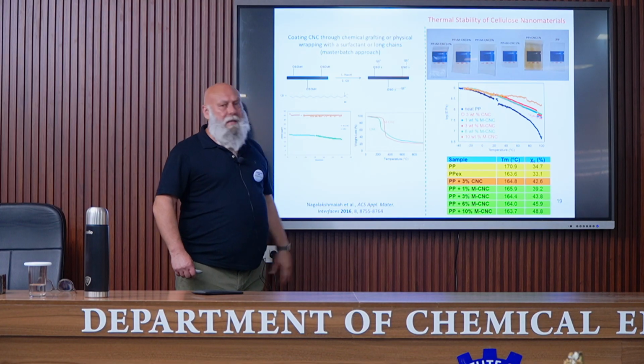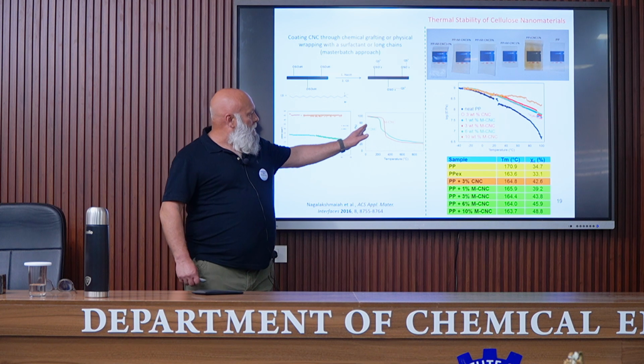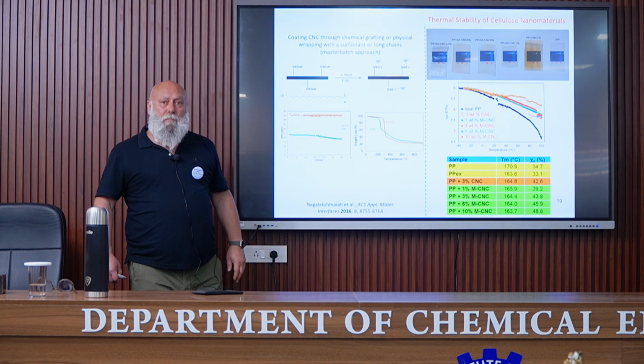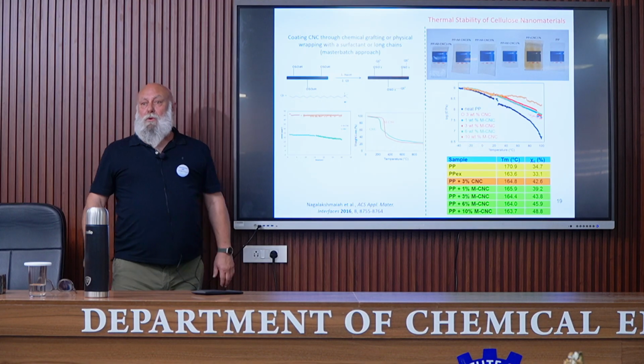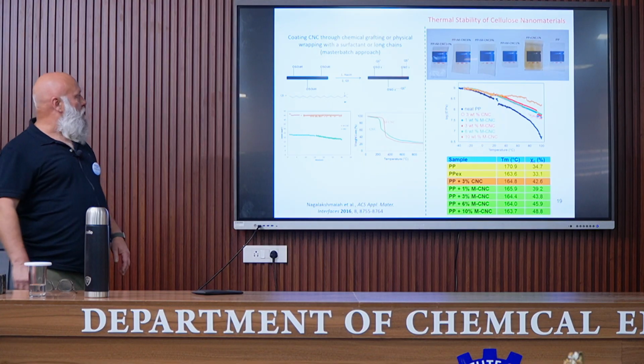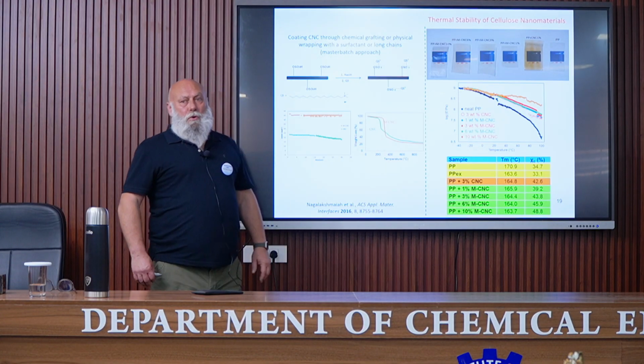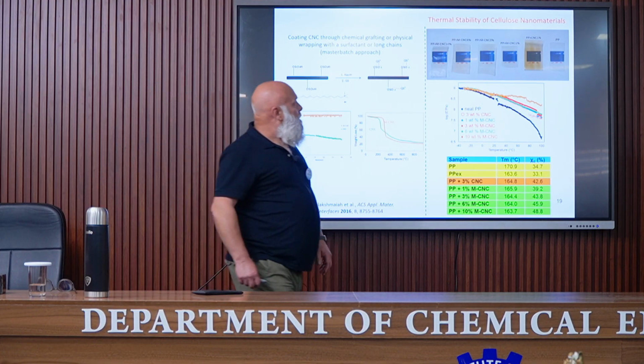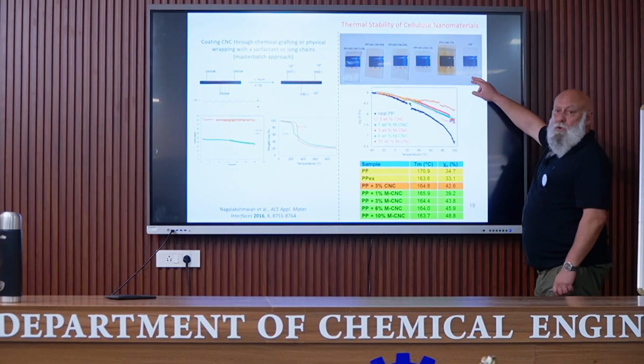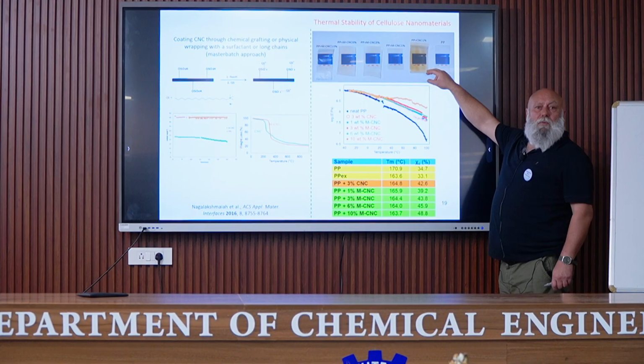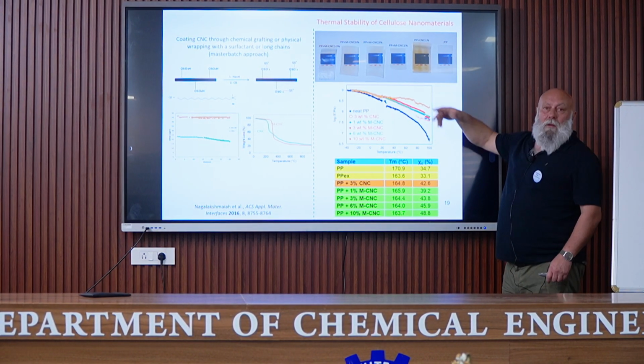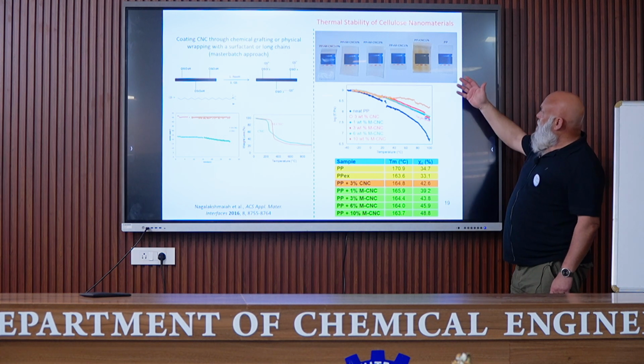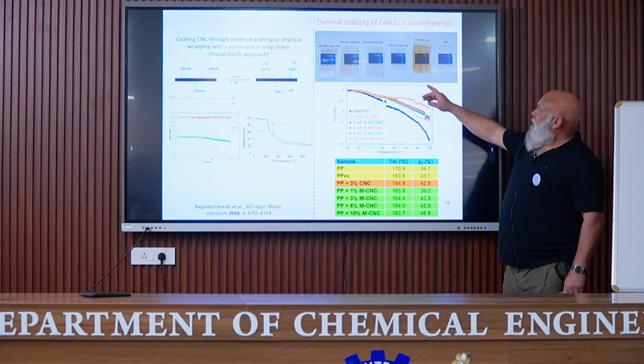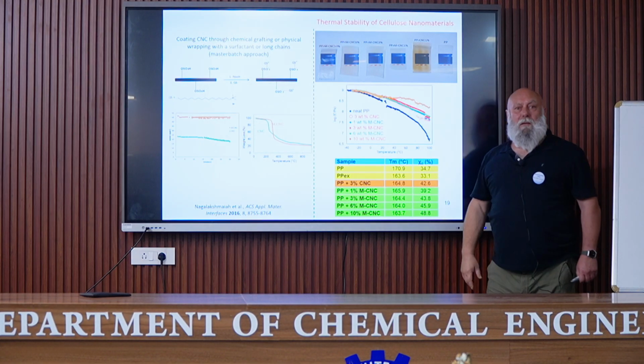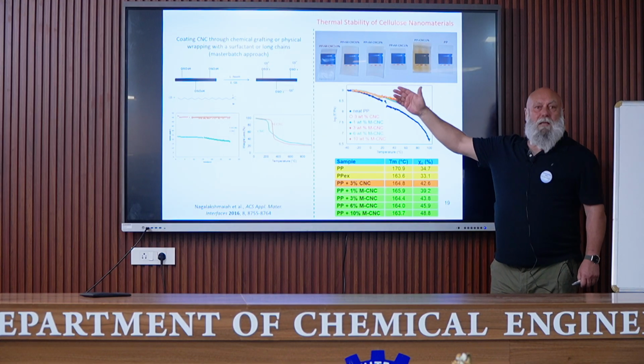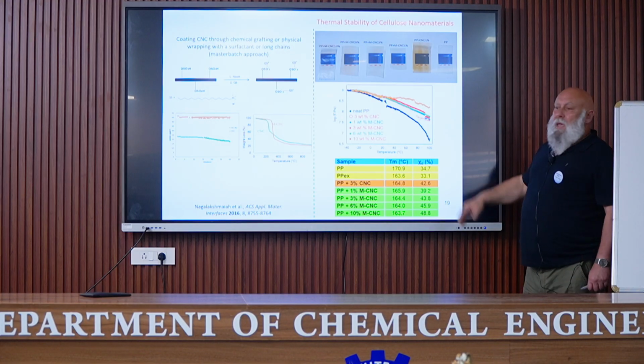At the same time, we can see from the TGA experiment that after modification, the thermal stability is improved because of the coating of the surface of the nanocrystals and then the coating of the sulfate groups. These nanocrystals have been used for extrusion with polypropylene. You can see here the aspect of pure polypropylene. Polypropylene that was extruded with 1% cellulose nanocrystals. You can see the thermal degradation of the material because it becomes yellow or brown. And when it was extruded with 1 up to 10% of coated nanocrystals, you can see that there is no thermal degradation.